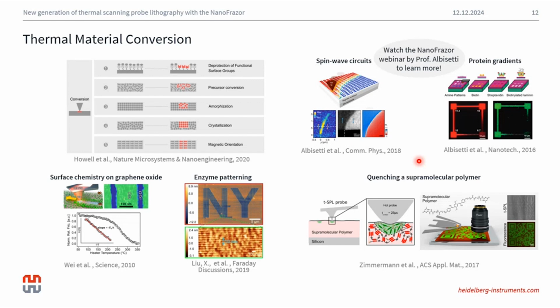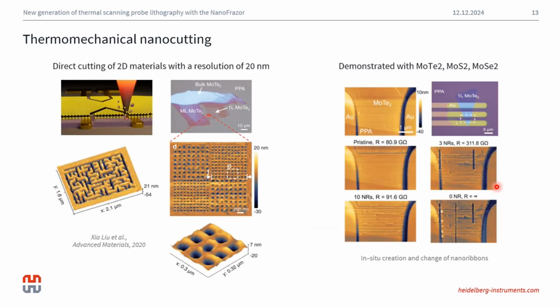Thermal material conversion with the heated tip was also applied to other bioengineering applications, for example, for direct enzyme patterning, quenching supramolecular polymers, and also creating protein gradients. Another way you could use the heated tip is for thermomechanical nanocutting. And this is very useful because typically it's very difficult to structure 2D materials using conventional lithography, as this is often using aggressive chemicals or a charged electron or ion beam that could damage the material's properties itself. In these examples here, the heatable tip was used to apply localized heat and pressure, and in doing so, the tip could accurately cut into 2D materials and create the patterns that you can see in these images.